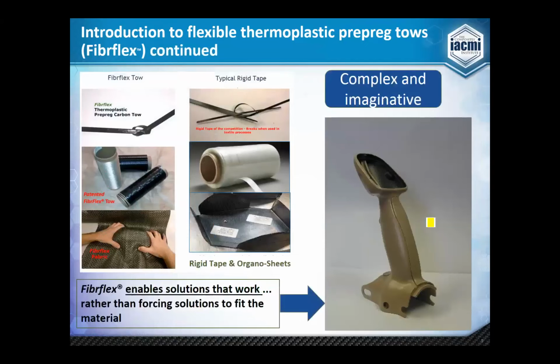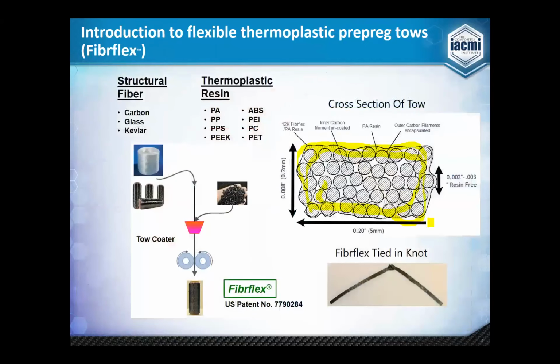Oh, I want to go back one other thing. Comparing this to, say, a thermoplastic prepreg tape, people may say that because the core is not wet out, it's an inferior product. Well, that's really not the case. With the resin being substantially where it needs to be in its final resting place, if you will, when you apply heat, pressure, and a little bit of time, the resin quickly migrates and wets out the toe. We've done substantial studies in that area to prove that. We get virtually void-free or very, very low void parts.